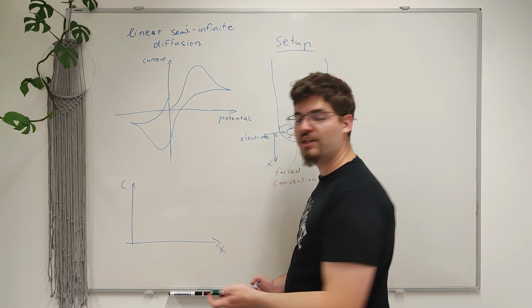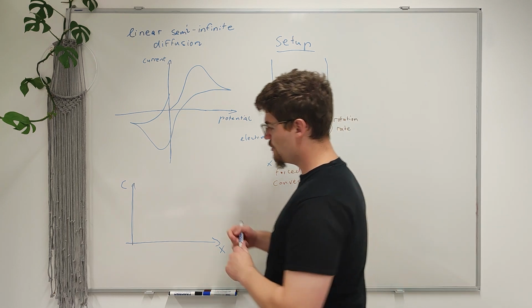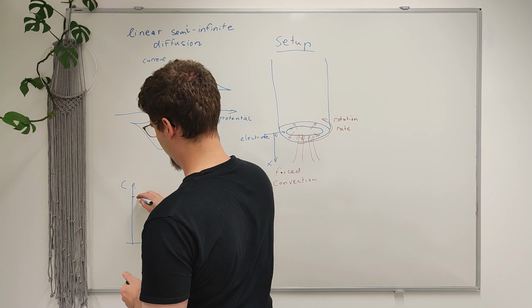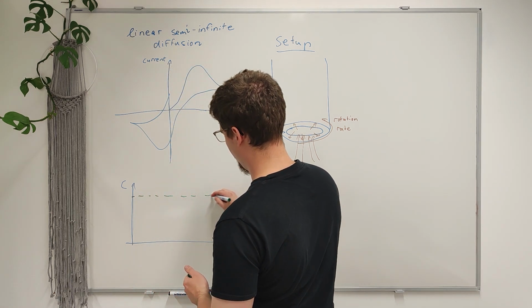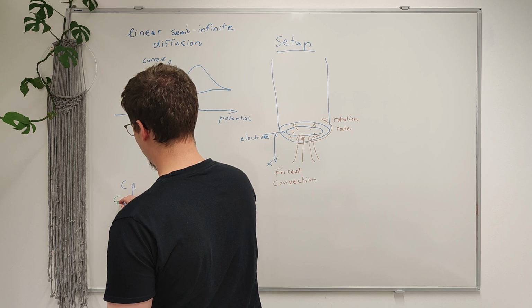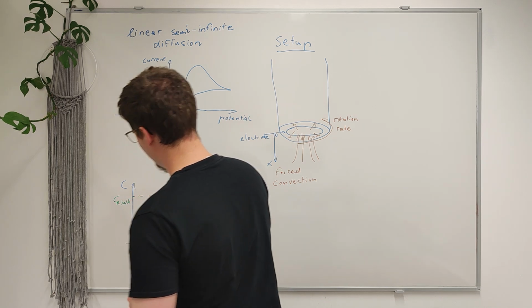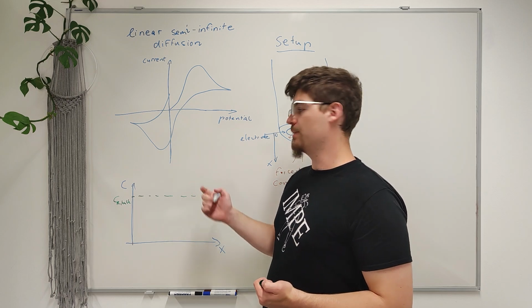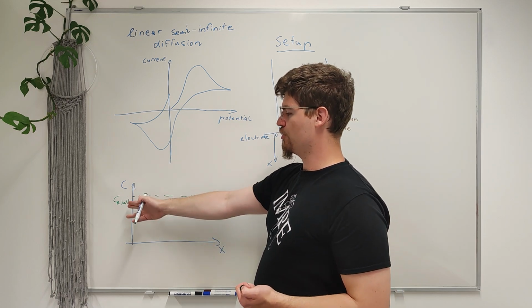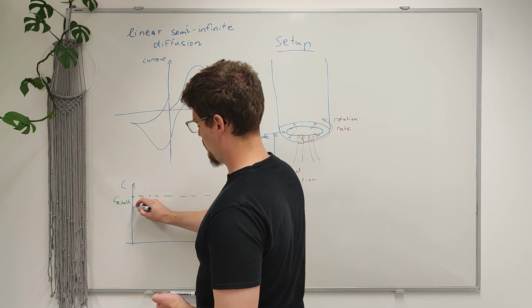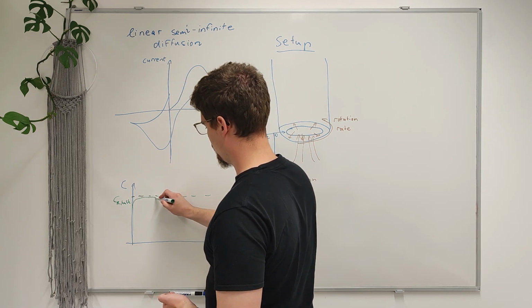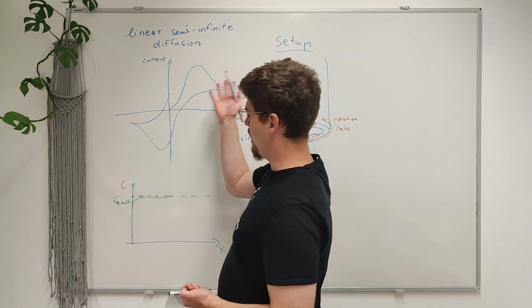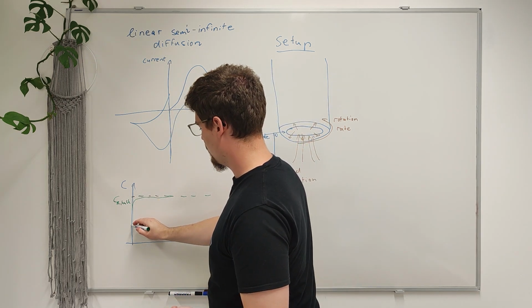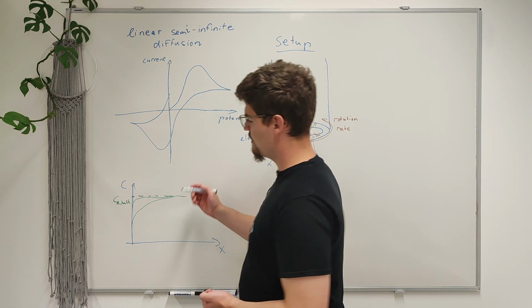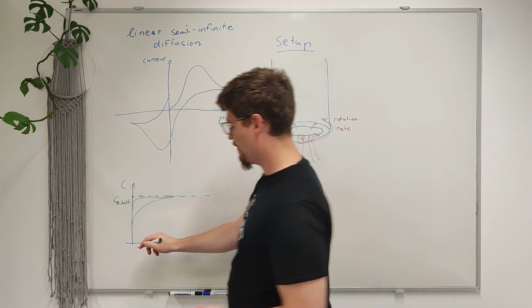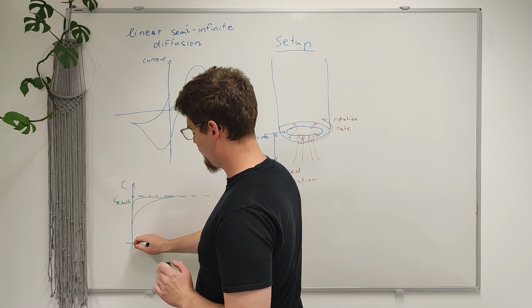And now let's plot the concentration along this direction. For this I will consider the reduced species. So the reduced species has a bulk concentration here marked by this dashed line, CR bulk. And now, as we begin to increase the potential, we decrease the concentration of the reduced species at the electrode. And as we scan in the forward direction, this concentration further decreases until it finally reaches approximately 0.